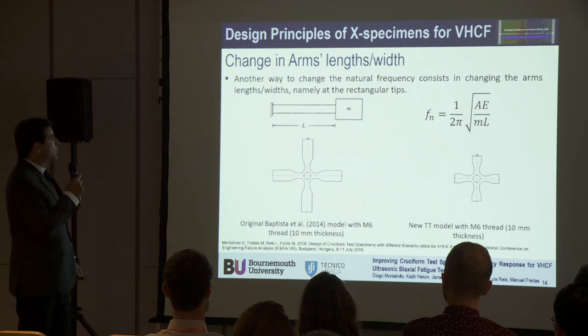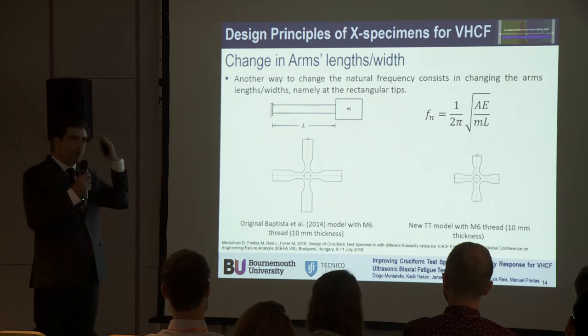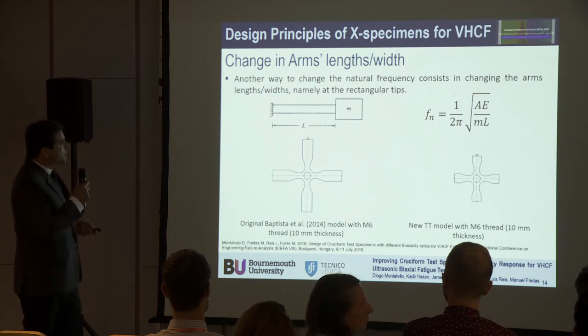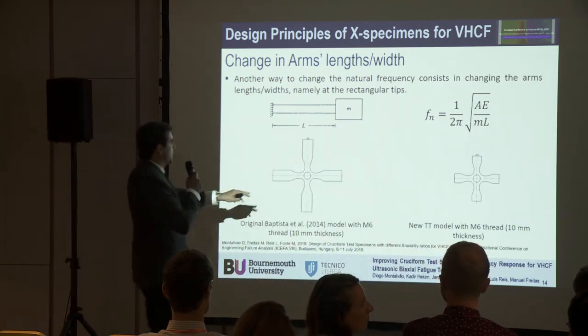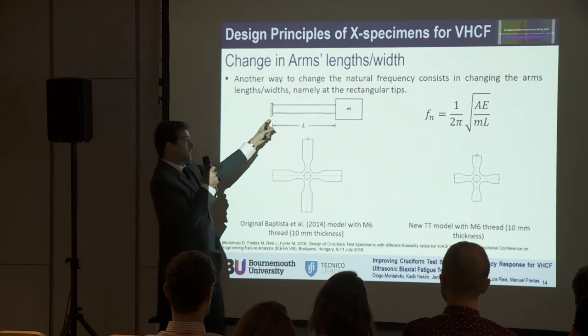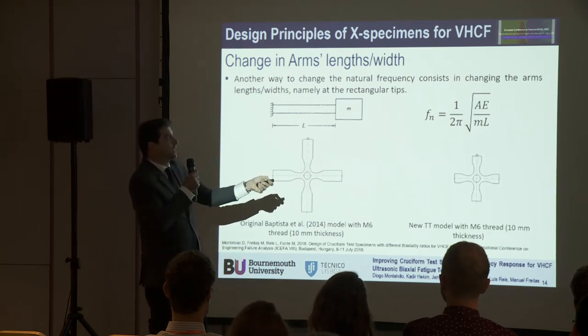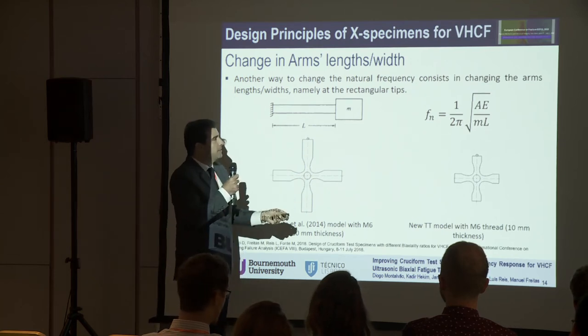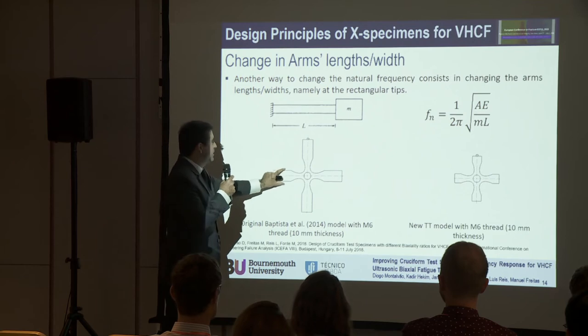The next published work attempts a different approach — more of a mindset for specimen design. We can think of the specimen as a massless beam with a mass at the tip, where the natural frequency is given by a simple equation. It's clear that if I cut a little bit here, the mass decreases, so the frequency goes up, and vice versa — so I can tune the specimens by changing these shapes.